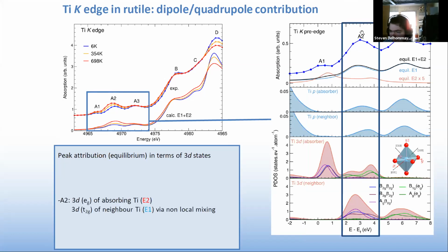If we look at the spectra, we can see that there are both E2 and E1 contributions, and so we know that this peak will involve both the absorbing P and the absorbing 3D states. And when we look at the density of states, we can see that there are both absorbing and neighbor 3D states. And so we know that this peak is related to both a direct transition towards the 3D EG states of titanium by a classical 1s to 3D E2 transition, but it is also a signature of the 3D T2G, this time of the neighbor, via non-local mixing. So in fact, there is a transition towards the absorbing P states that are mixed with the neighbor titanium 3D T2G states, sorry.